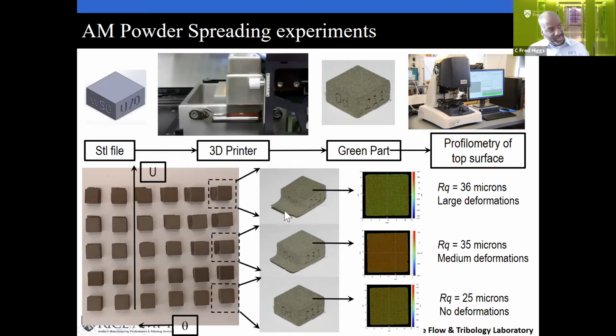So the first one, the bottom layer, once you put the second layer on, it's sheared, right? So you get to the top, you have a cuboid that's distorted. And then we improve it through trial and error. And then finally, you get a nice, perfect cuboid here by changing the quality of your spread. But we're going to do that in a more intelligent way with modeling. So here you can see we brought the cuboid into the lab with our optical surface profilometer. We can get surface roughness on top, and you can see it decreased here. We also can see it had no deformation. So we call this the winning cube.